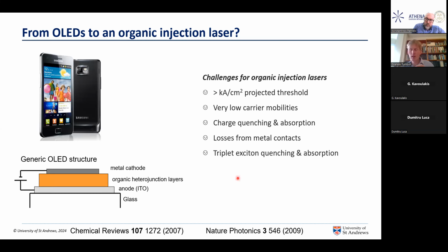In order to have a low operating voltage, you also need to keep your contacts close together, and so you end up with potentially losses from the metal contacts. In addition to that, we inevitably generate a large number of non-emissive triplet states when the electrons and holes recombine, and they also quench the light emission and also absorb light. So this is all very difficult, and people have looked in the field for 20, 25 years to try to get over many of these problems, and many of these problems along the way have been solved or addressed in one way or another.